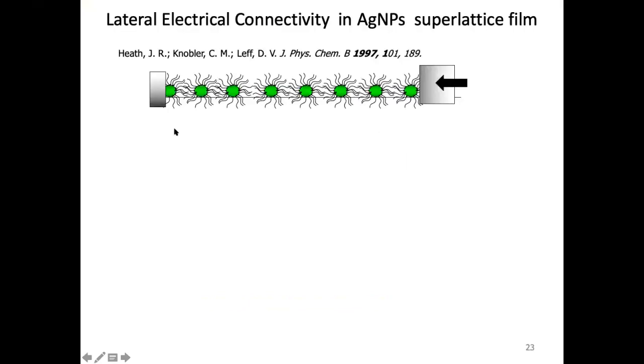Basically, here in this case, how do you prepare this 2D superlattice? One can prepare silver nanoparticles or gold nanoparticles, capped with a capping agent like I have shown over here, and you can pour this solution at the liquid-air interface. It is called a Langmuir-Blodgett film. It will form a layer of silver nanoparticles floating on the surface. Since they are at equal distance, they are basically adjacent in a hexagonal close pack on the surface.